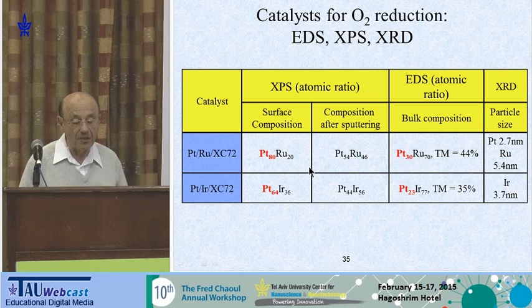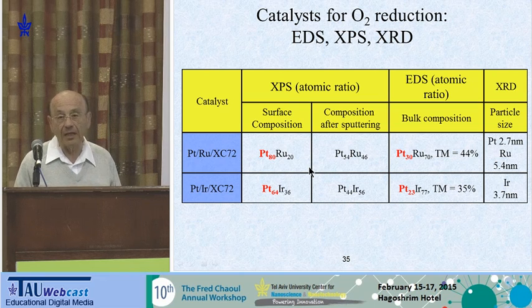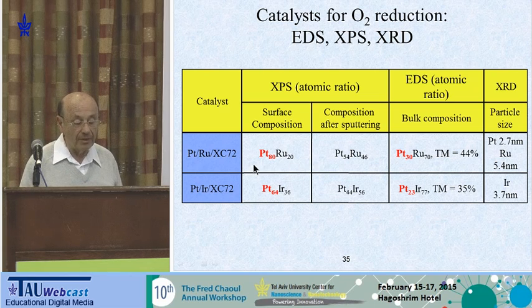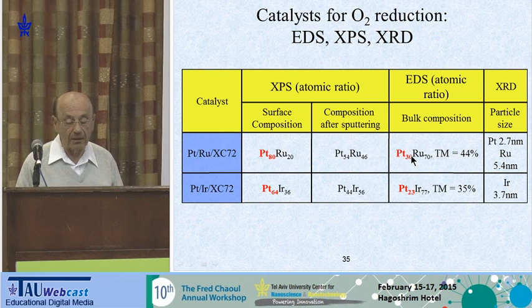Now, using XPS and EDS is one piece of evidence, and we also have electrochemical evidence for that. For example, in platinum on ruthenium, we get 80% platinum atoms at the shell and 30% platinum atoms in the core. That's close to 3 times more platinum on the surface, on the shell, than in the core. And the same for iridium. This is platinum on iridium, and we have again 3 times more platinum on the shell than in the core.